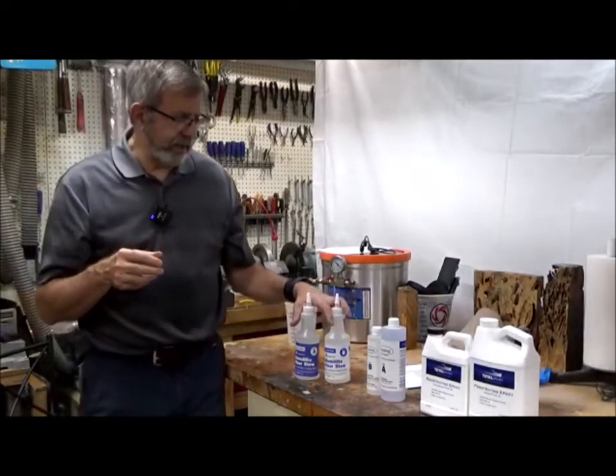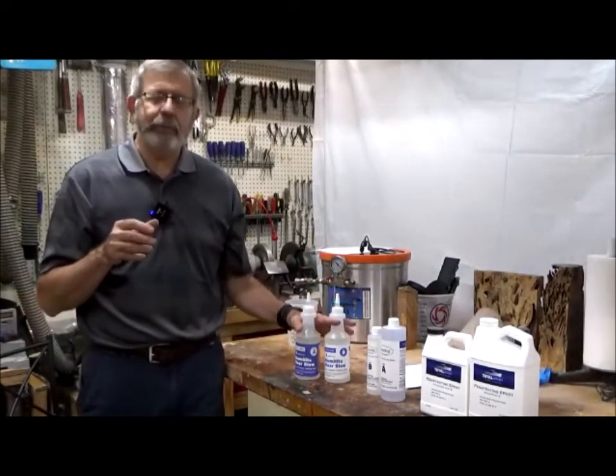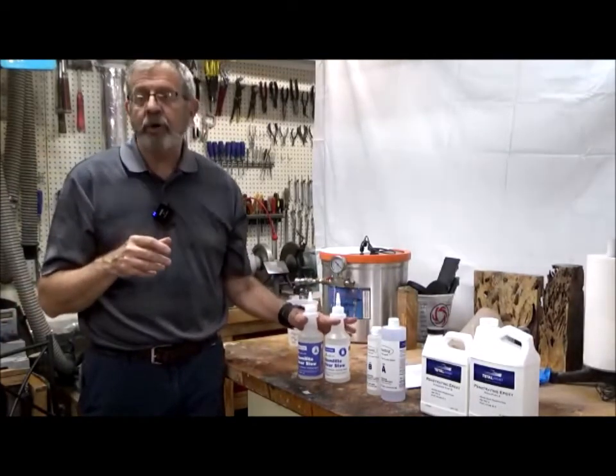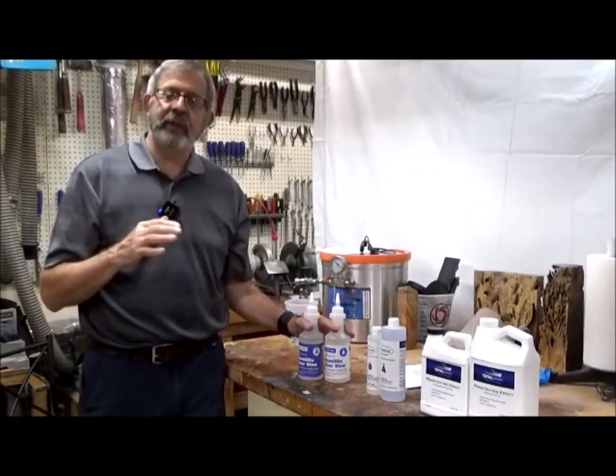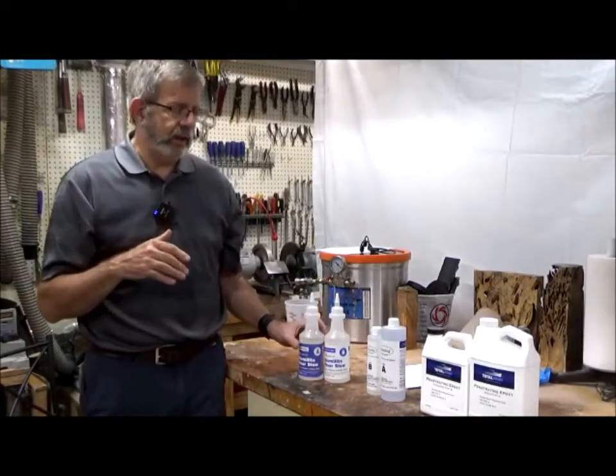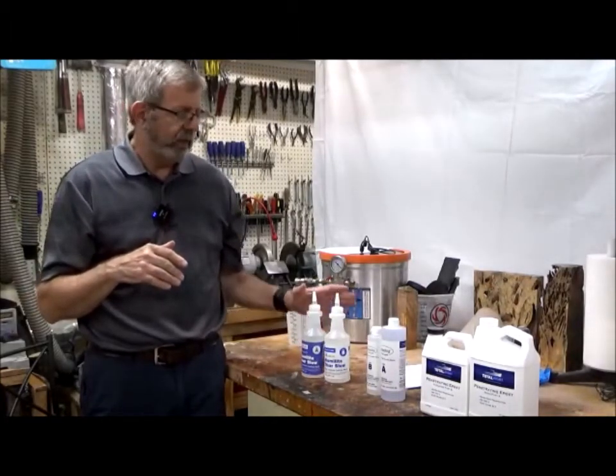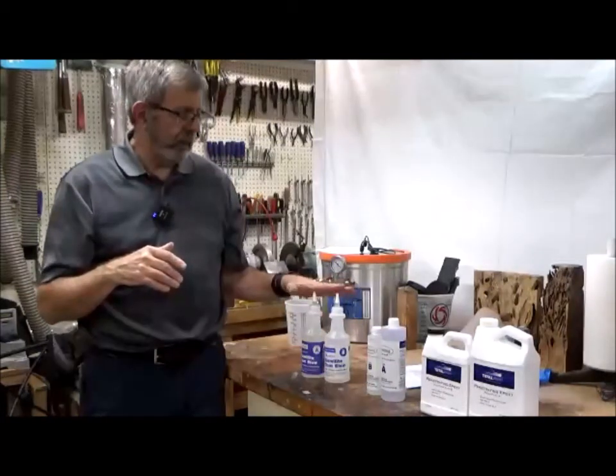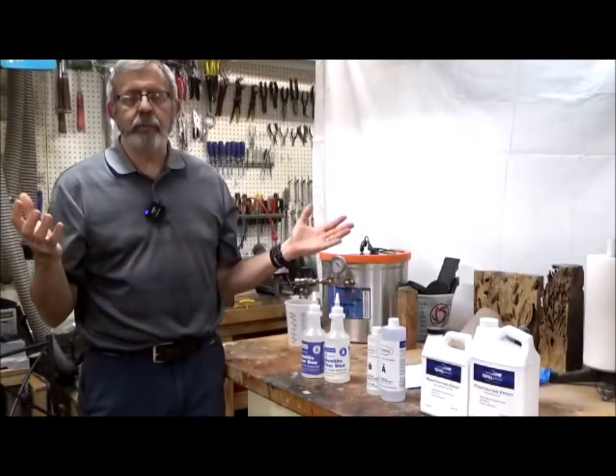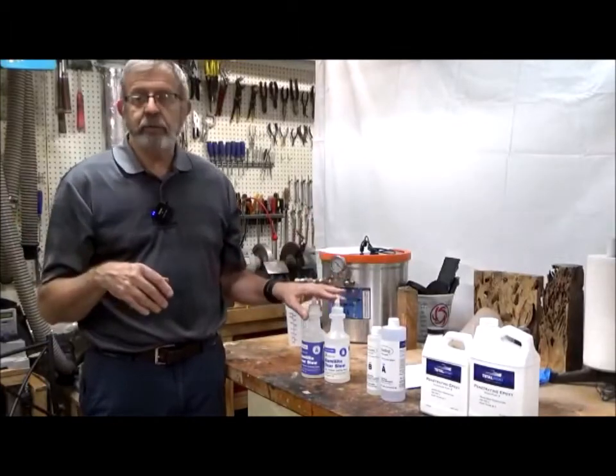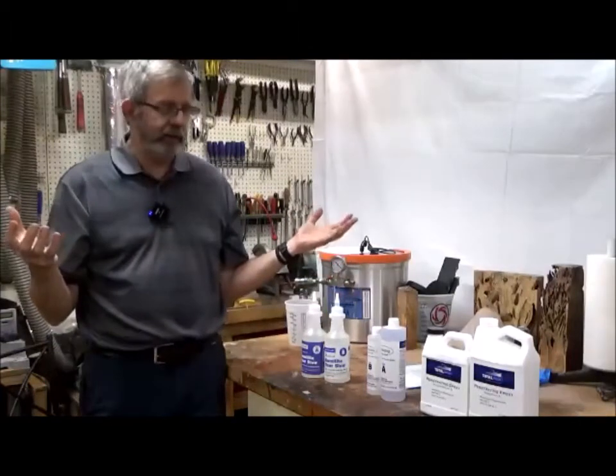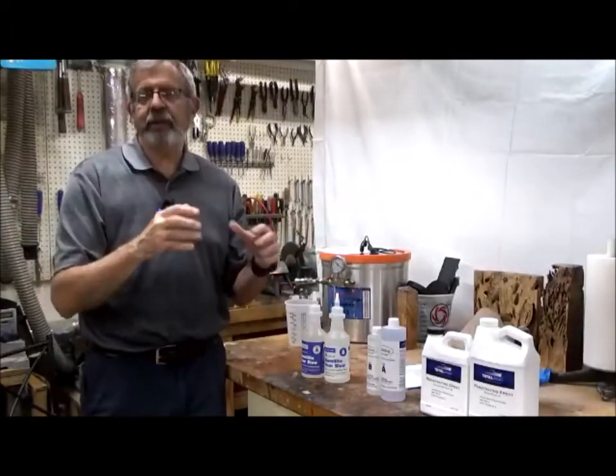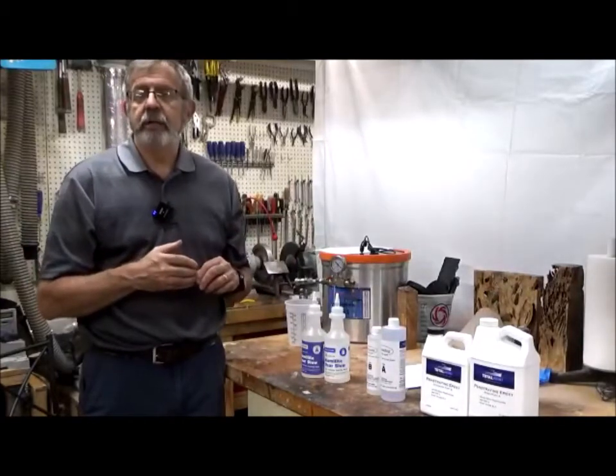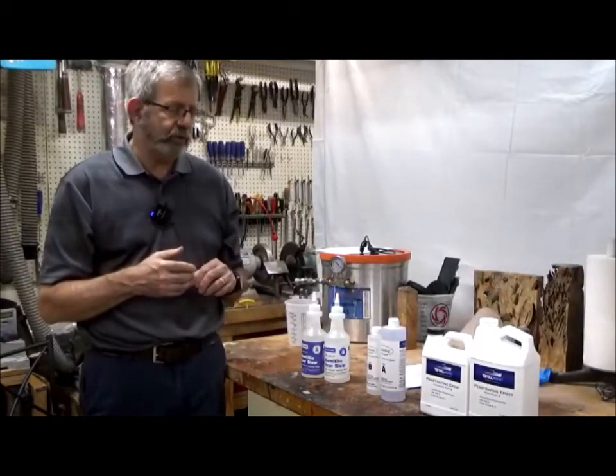The polyurethane resins are mixed one-to-one by weight. So you mix these with a scale and you just weigh them out and you put equal parts A and B and then you mix them. And what I do is I mix them in two different cups and then pour them together, because your working time is so short.